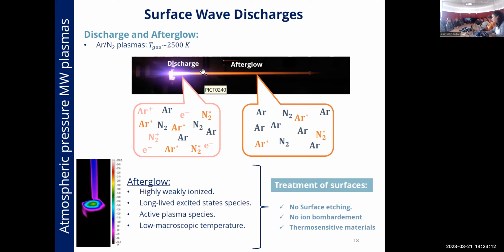Something interesting and very important is that despite having these excited particles all along the afterglow, if we move from the start of the afterglow to the end, the gas temperature decreases a lot. This allows us to treat thermosensitive materials like seeds, food, and also polymers. It's also interesting that since we don't have ions in our afterglow, there is no ion bombardment on the surface and no surface etching. So we can take advantage of this specific part of the plasma.